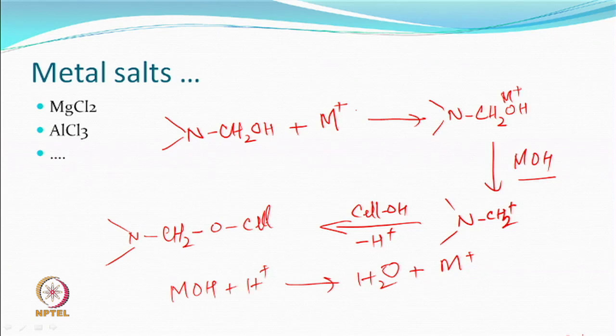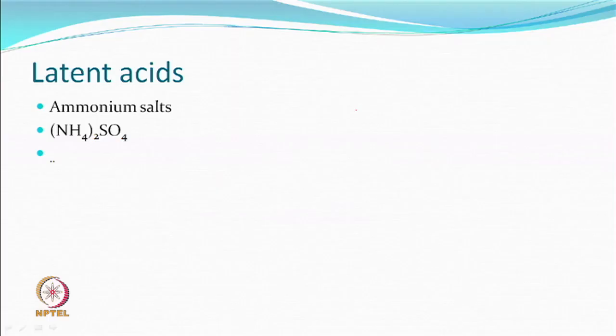So therefore, the probability of its effectiveness is good, but it is not more degrading because this process starts only after a certain temperature. You can store it at room temperature, not much will happen. But if you store sulfuric acid based fabric at room temperature, things will keep happening at room temperature as well. So that way it reduces the strength loss and is still effective. Similar compounds like latent acids, which are ammonium salts, at room temperature are not very effective, but at higher temperature ammonia will be liberated and suddenly they will become effective.